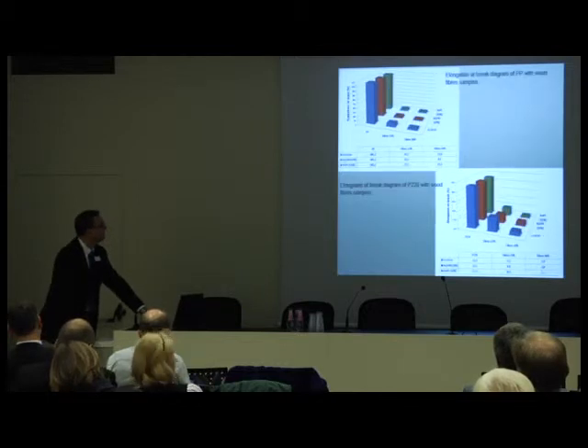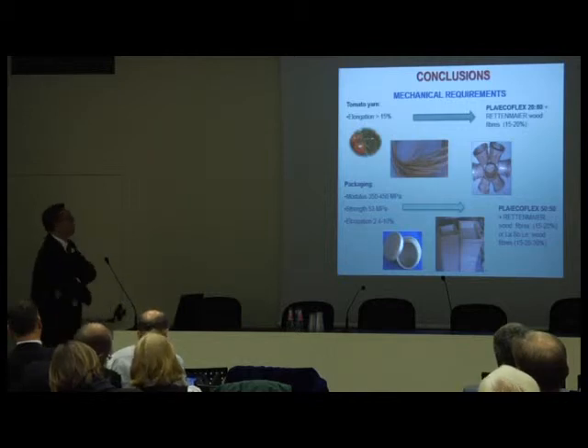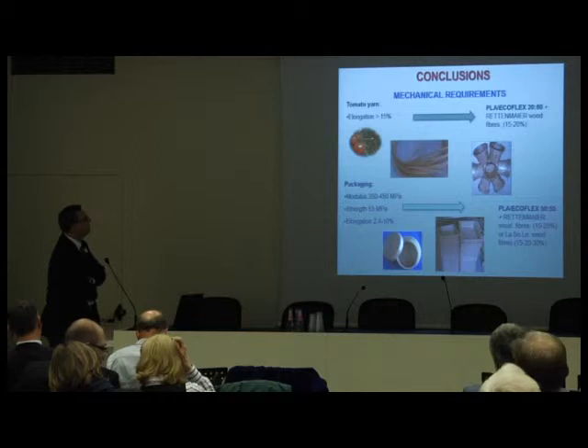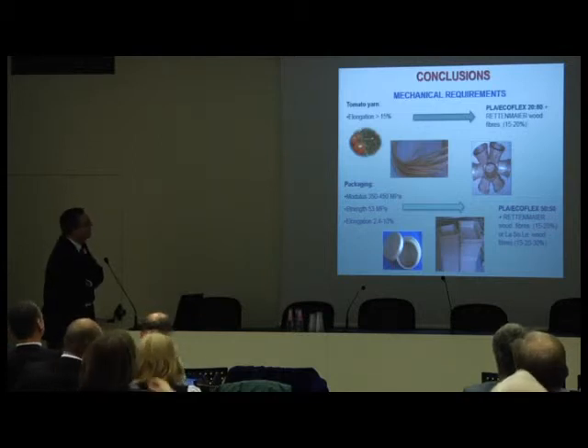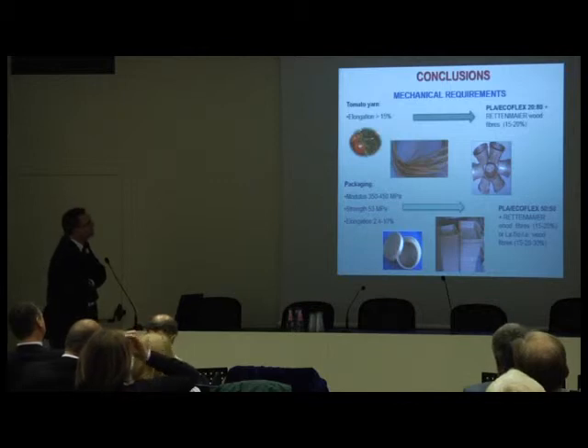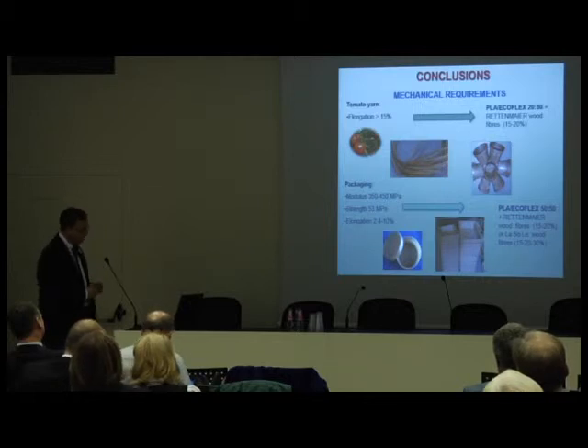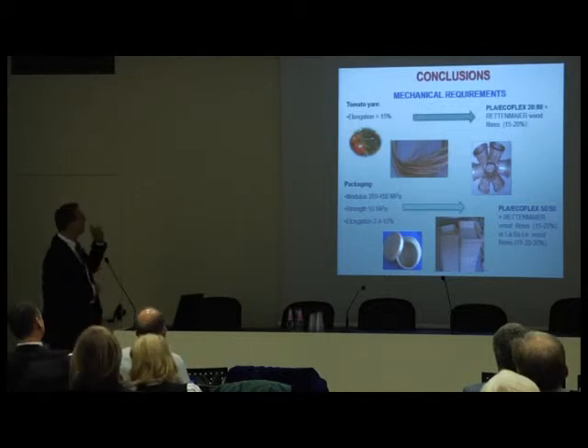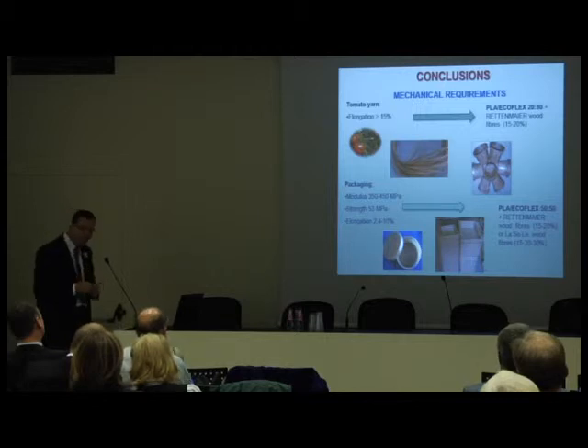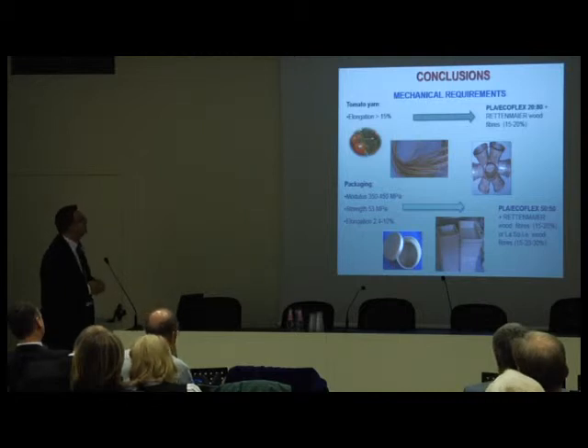I cannot go too much into detail because time is running, and if you are interested, I can give you details later. We also skip this because it's a bit far. Okay, some applications we produced during the project. You see, the tomato yarn is based on PLA Ecoflex with 20% PLA, 80% Ecoflex. Very soft material, so we could add up to 20% fibers and maintain some ductility. And this is for tomato plants, to keep them stable. And so we can make a knit with them.